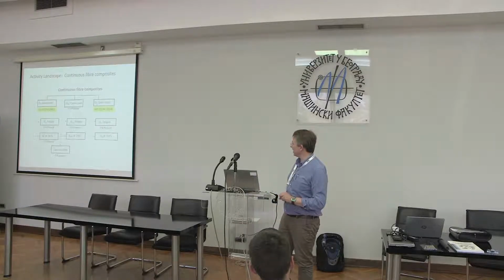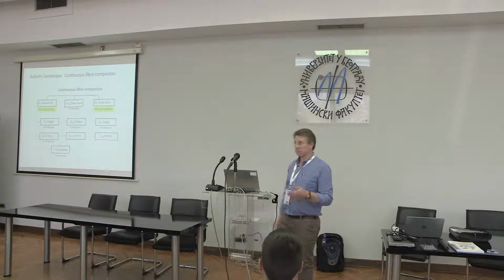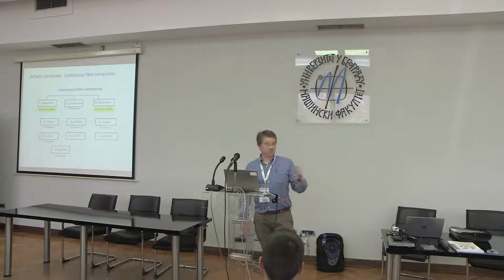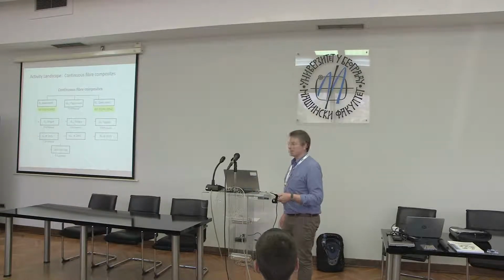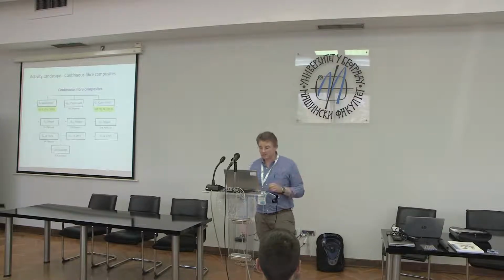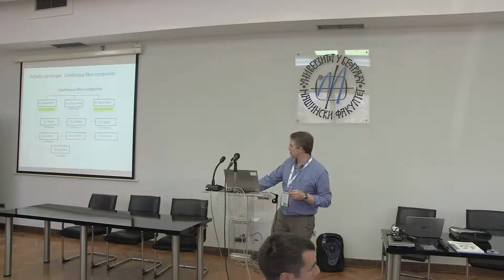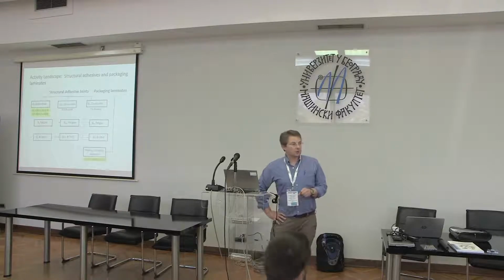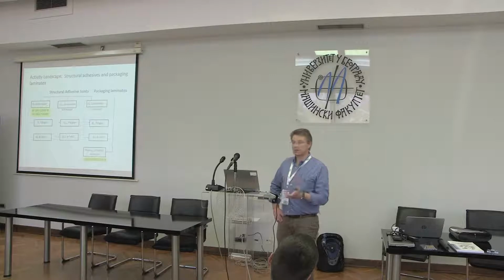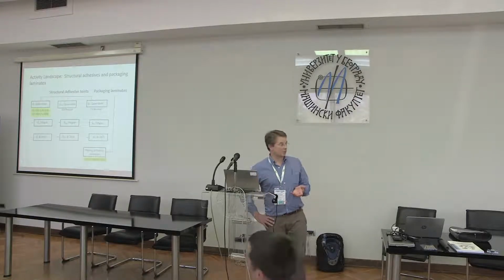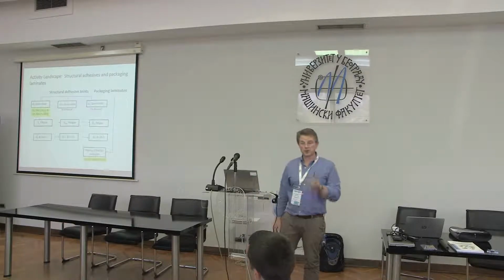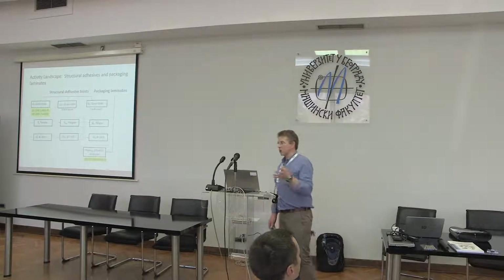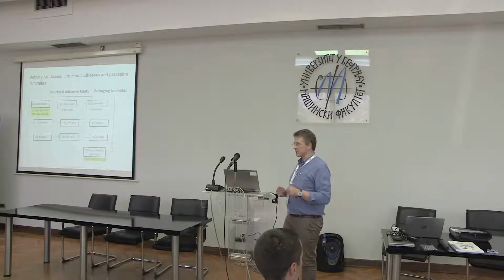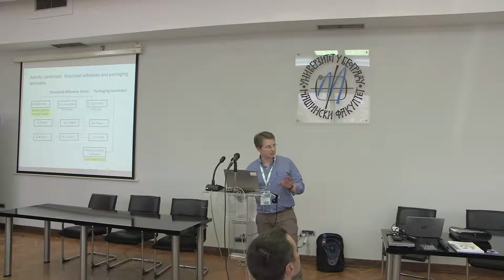Now the ones that have been highlighted in yellow are ones where international standards have been developed, as a result of not always entirely ESIS TC4 activities, because for international standardization, sometimes you need, for example, ASTM to also agree, although ASTM, of course, have their own range of standards, and groups like the Japanese group and the European one. But ISO standards are usually the goal of what this particular technical committee is trying to develop. Just very briefly, with adhesive joints, I'm not specifically talking about adhesives this morning, but many of the things that we say about a composite material are also relevant to an adhesive joint, because we're talking about a laminate. Typically with a structural adhesive, we're talking about a thin adhesive layer between two rigid substrates. That has a lot of analogies to a composite where you have a matrix and rigid fibers, so it tends to follow the same basic trend as the activity for composites.